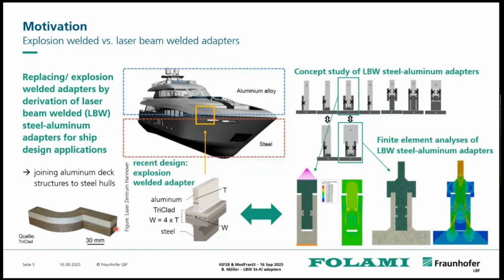In this process, we also need a technically pure aluminum layer in between these two, which limits the strength. And then from this, there is a design and welding of an aluminum structure and a steel structure to be implemented in such a ship structure. So our starting point was how an adapter made of steel and aluminum, to be used in laser beam welding, could look like. Therefore we had a first conceptual study giving some outcomes and then performing first finite element simulations before moving over to fatigue testing and validation.